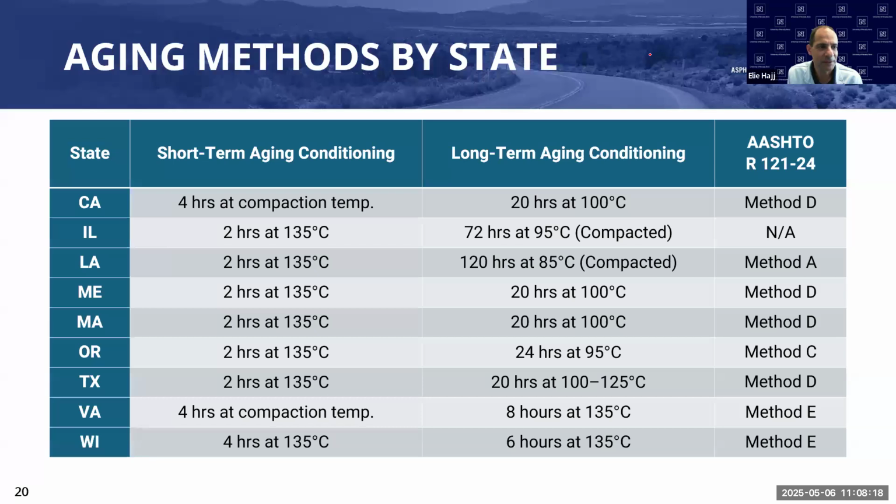So binder stiffness seems to be used very commonly as a starting point to see where to target, how many hours, and then you try to bracket that and then validate this with your BMD mechanical test. Yep.